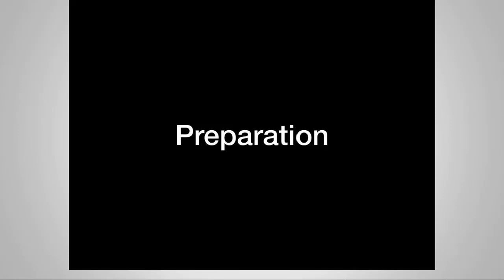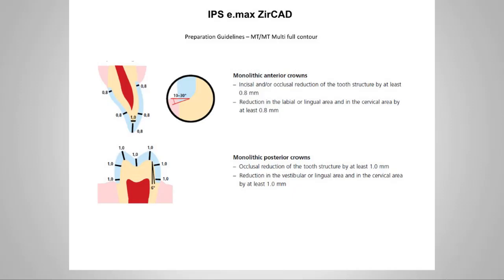Let's talk about preparations, because there are some preparation criteria for zirconia that are important. Once again, if you're using the Zircad, the Ivoclar zirconia, there are a couple of guidelines. Remember, the different zirconias with their different strengths have minimal requirements as far as reduction. This is going to be the preparation guideline for the MT and the MT multi full contour. Once again, this is the more aesthetic one, with a higher yttrium stabilized molar percentage, the 4 molar percentage.